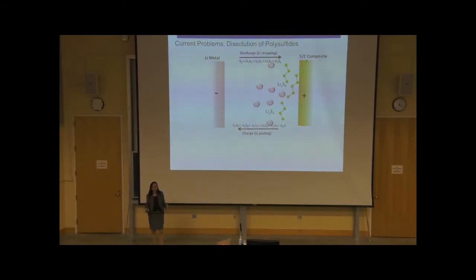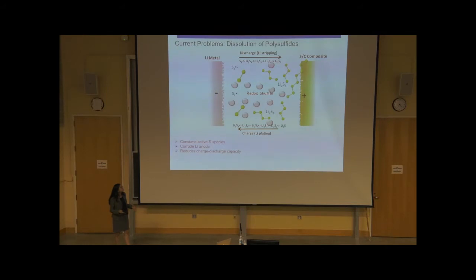And this is great. These are high energy chemical reactions. We can store a lot of energy by doing that. The problem arises when these lithium polysulfide species start migrating toward the anode side along with some highly reactive radical anions, and then they corrode the surface. And this happens every time we charge and discharge the battery. So it ends up eating all of the active sulfur species. It corrodes your lithium metal anode and reduces the charge-discharge capacity of lithium sulfur batteries.